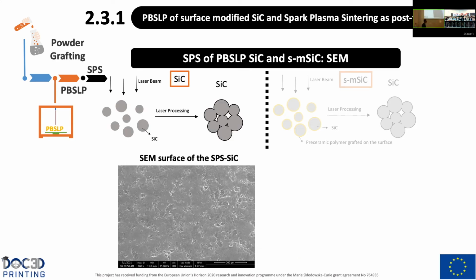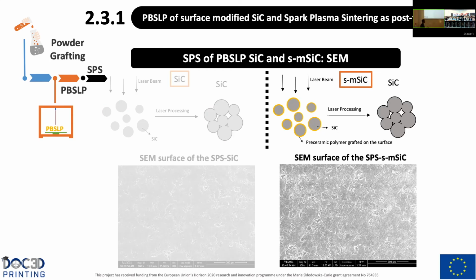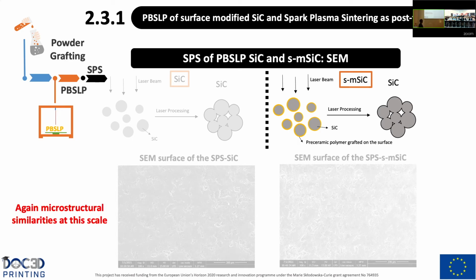So regarding the microstructure of the silicon carbide after post-treatment, here we can observe, of course, a reduced porosity comparing this sample with the previous one manufactured by additive manufacturing. And very similar, here we can observe again for the surface modified silicon carbide a reduction in the porosity as well. So actually here again, we have some microstructural similarities at this scale.